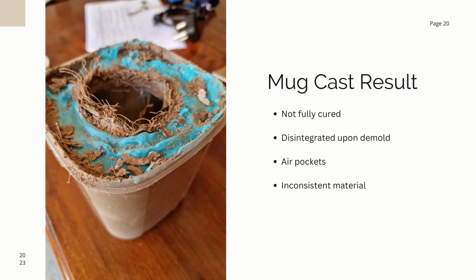There were quite big air pockets. That was probably due to us trying to shove the aluminium sleeve into the biomaterial, so basically squishing it up and out to fill up all the gaps, and that obviously led to quite a big air pocket within it, and it was also inconsistent material because when we put in the aluminium cup it got closer to one side of the mold than the other, so some of the material was more on one side than the other, and obviously that in the final product did not do. It should be consistent around the whole cup.